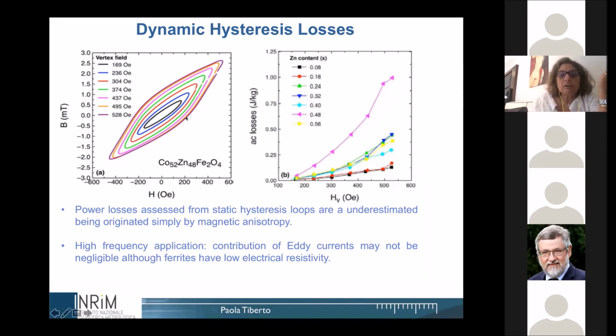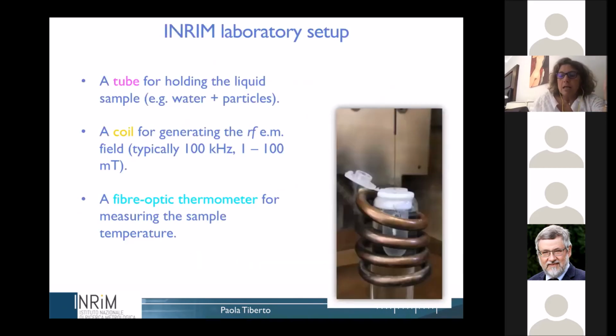Again, here is the behavior with increasing field of the cobalt 52 zinc 48 composition, and here is the behavior with zinc content, and zinc 0.48 is the one that has the highest losses, so it can heat more, it can release more heat. We have always thought that here the contribution of eddy currents may not be so negligible because of these non-monotonic results.